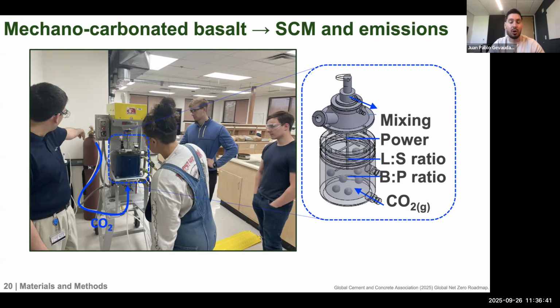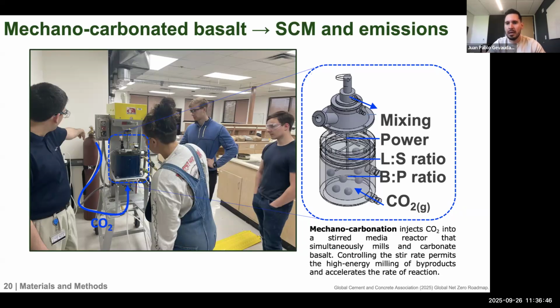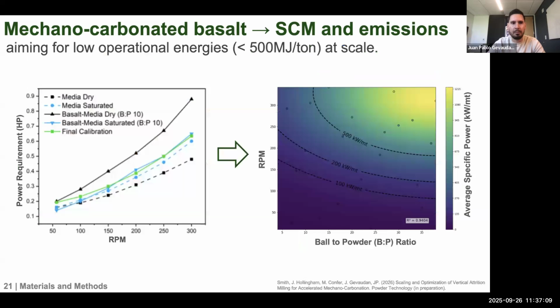In this case, for mineral carbonation, those ions of interest are calcium and magnesium. So we have termed this process mechano-carbonation because we're simultaneously milling that basalt, mechanochemically activating the basalt, while also triggering carbonation reactions to create magnesium carbonates or calcium carbonates. So it's a simultaneous process that we're using here. Now, I would be remiss not to mention this. We are aiming for low operational energies at scale, less than 500 megajoules per ton. And that is really, really important.